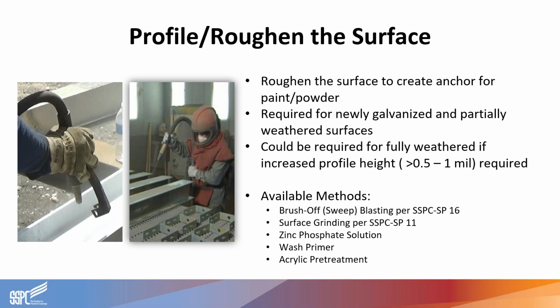And then needs to give some input on the methods that are available for surface roughening. So the available methods, depending on whether you're painting or powder coating, may be brush-off blasting for SSPC SP16, which we mentioned earlier, that is the most common. Surface grinding in accordance with SSPC SP11. The use of a zinc phosphate solution, or the use of a wash primer or other type of acrylic pretreatment. So I'm going to review some of the considerations that can arise in each case.